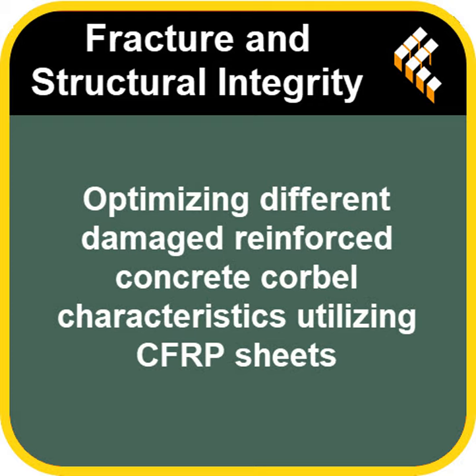That comparison is fascinating, too. And here, the type of wrapping mattered. The side-wrapped specimens, Configuration 1, consistently showed greater load improvements than the strip-wrapped ones. Okay. Example? Sure. For the specimens damaged to 50%, the side-wrapped one, RCS51, saw a 13.73% load increase after strengthening. Pretty good. Yeah, but the strip-wrapped one at the same damage level, RCST52, only got a 9.86% improvement. So side wrapping was clearly better for restoring strength in damaged corbels.